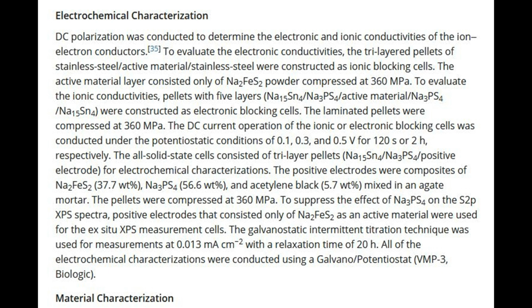The all-solid-state cells consisted of tri-layer pellets, Na15Sn4/Na3PS4/positive electrode, for electrochemical characterizations. The positive electrodes were composites of Na2FeS2, 37.7 wt%, Na3PS4, 56.6 wt%, and acetylene black, 5.7 wt%, mixed in an agate mortar. The pellets were compressed at 360 MPa.